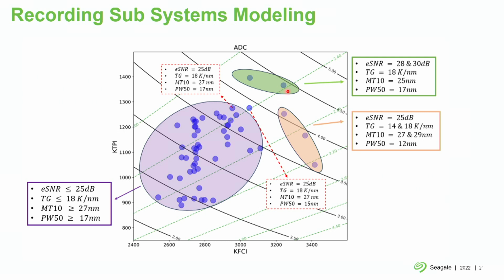The most we've been able to model without really having to change the architecture of the system is about 4.5 terabit per square inch. So it's over 8 terabyte per disk, which would be 80 terabyte drives if there were 10 disks in a drive. This is assuming that we're just scaling the components, and assuming we can scale them so aggressively, we think maybe 8 terabyte per disk is possible, or 4.5 terabit per square inch. But we don't really want to stop there.